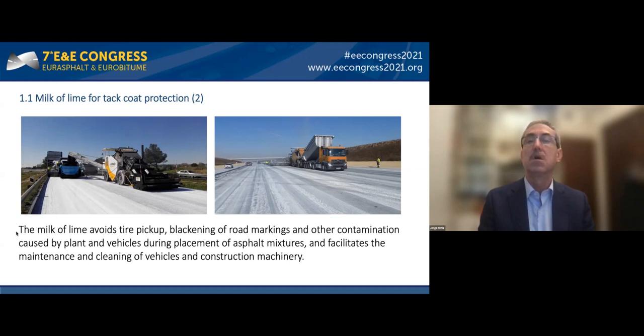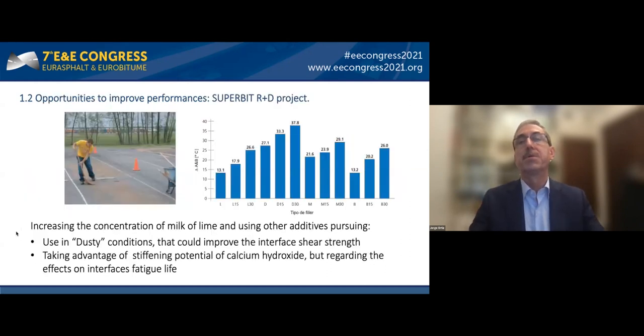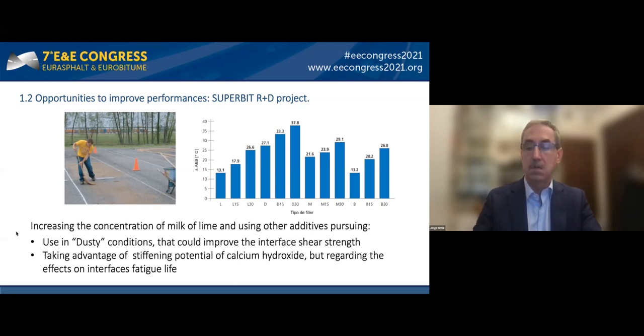The milk-of-lime application has at least three effects related to the integrity of the tack coat preservation. Calcium hydroxide particles prevent direct contact of the residual binder film to the tires of work vehicles. Surface wetting reduces the temperature of the binder film, limiting the tire pickup capacity, and the temperature of the top surface of the existing pavement is also reduced as a result of the water emulsion evaporation, helping to safeguard the integrity of the binder film.